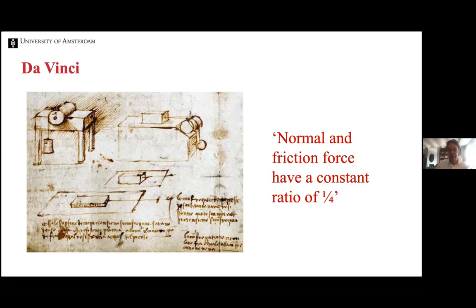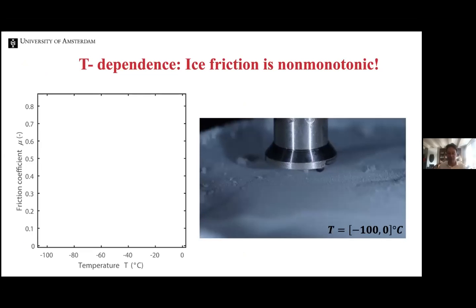Okay, so let's do an ice skating experiment in a laboratory that looks like this. This is a Rheometer tool, so we abuse a Rheometer to do our friction experiments, and our friction experiment consists of having a little metallic ball, which is our model skate, if you like, that we slide over an ice surface in between temperatures of -100 degrees and 0 degrees. And that is important because the large temperature range actually allows us to say many interesting things about the friction.